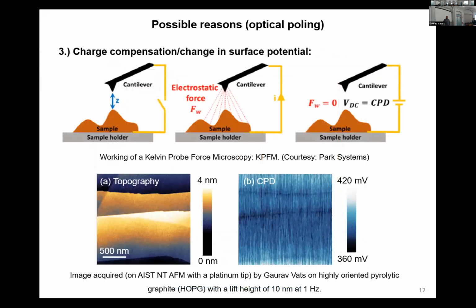Now to study the third possibility of charge compensation and change in surface potential, I use this technique, Kelvin probe force microscopy. So in this, what I do is we have a cantilever. I bring it close to the sample at a height of say Z. It could be somewhere between 20 to 50 nanometers. It experiences an electrostatic force which we try to balance, and we call that potential the contact potential difference. So this contact potential difference gives us an idea of the surface potential, and we can estimate the work function of the material as well. So here I have shown this measurement on a test sample, which is HOPG. So we use this to calibrate our measurements.